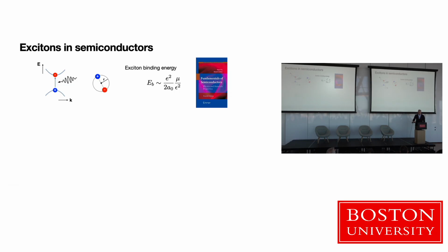It's like a modified hydrogen atom, except one of the components is much lighter than the proton, and that leads to this mu effective mass. And it lives in a solid, and so it's got a dielectric constant in the denominator. So essentially you have the Rydberg with this modification that involves the effective mass and the screening. And so when you shine light on the system, that electron and hole are bound.